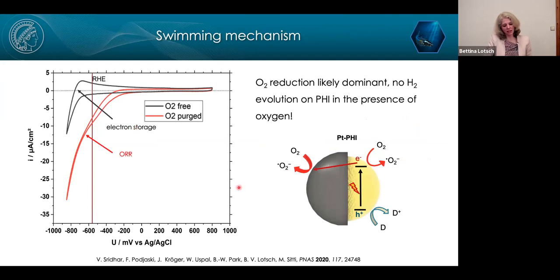What we also noticed as a side remark is that most likely in these systems, if we look at them under ambient conditions, meaning there is oxygen in the solution, then we do not observe hydrogen evolution as is normally assumed. Normally, in the literature with platinum capped titanium dioxide, it is assumed that hydrogen evolution is one source of propulsion. But what we could clearly show is that before hydrogen can actually be evolved, oxygen from the environment is consumed by being reduced. And that is most likely the dominant propulsion mechanism along with the oxidation of the fuel. So that's more or less a side remark.